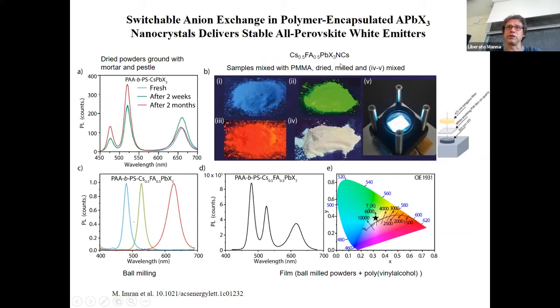Now, in this case, we made the cesium formamidinium lead halide nanocrystals. In the case of the bromide, this corresponds exactly to the green emission from the powder. Then we use part of them to make an ion exchange, to generate the blue and the red components. And in all these cases, the final nanocrystals, the dried powder, were mixed with polymethyl methacrylate, dried, and ball milled to achieve an extremely fine powder.